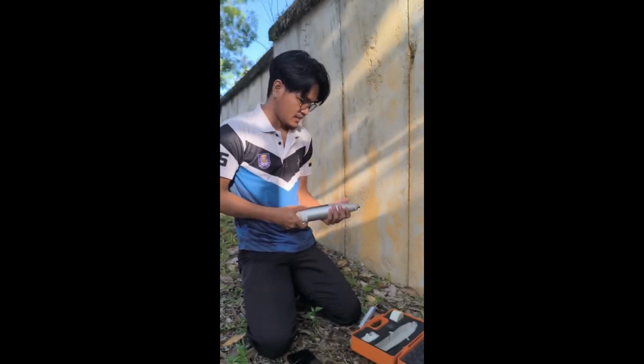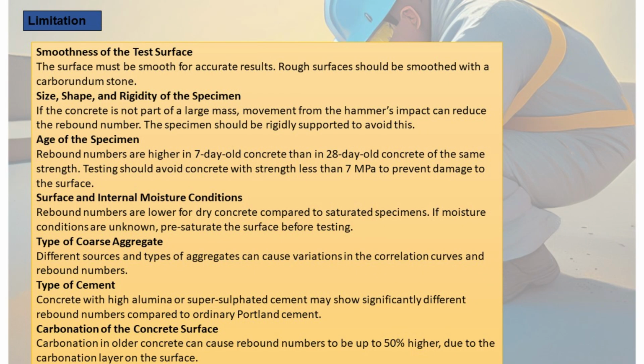While the Schmidt rebound hammer is a quick and inexpensive way to test concrete uniformity, there are important limitations to consider. First, the surface must be smooth for accurate testing. Rough surfaces should be smoothed using a carborundum stone. If the specimen is not part of a large mass, movement during impact can reduce the rebound number, so it should be rigidly supported. Rebound numbers are typically higher for 7-day-old concrete than for 28-day-old concrete of the same strength. Rebound testing should not be done on low-strength concrete, less than 7 megapascals.